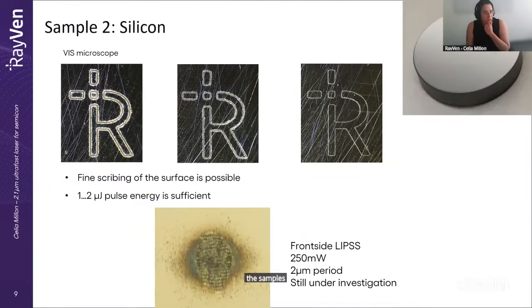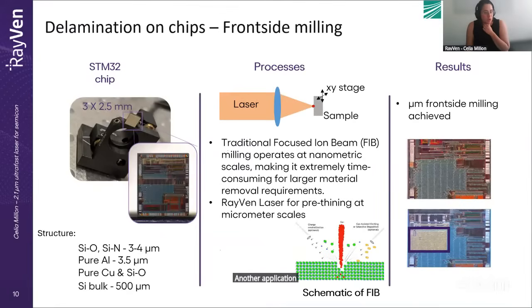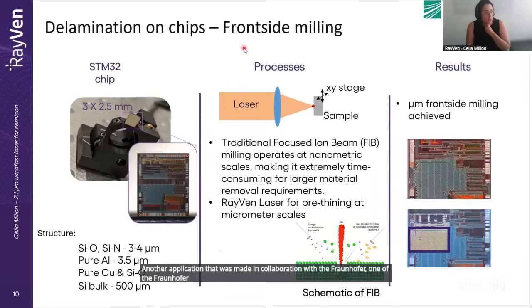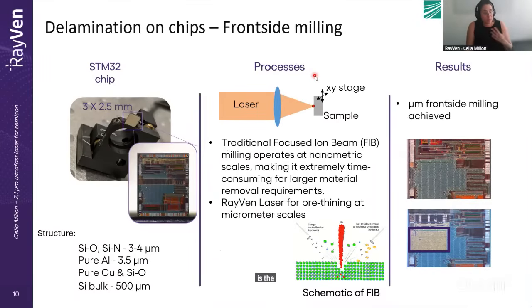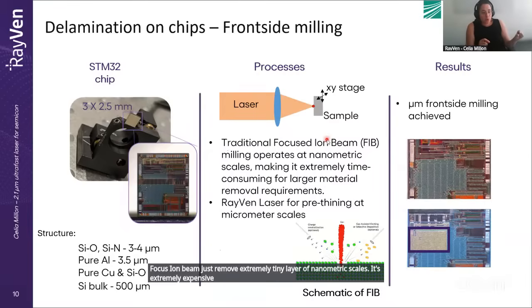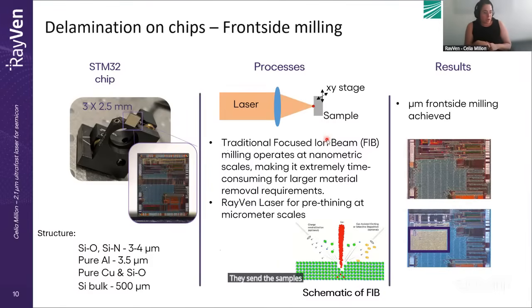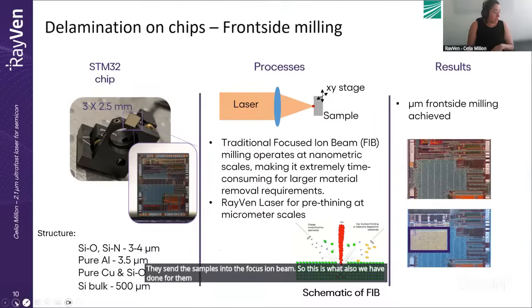Another application that was made in collaboration with one of the Fraunhofer institutes is the pre-thinning of samples before a focused ion beam. Focused ion beam just removes extremely tiny layers at nanometric scales. It's extremely expensive. And they were looking for a tool to do the pre-thinning at micrometer scales before they send the samples into the focused ion beam. So this is what we have also done for them. They were happy.